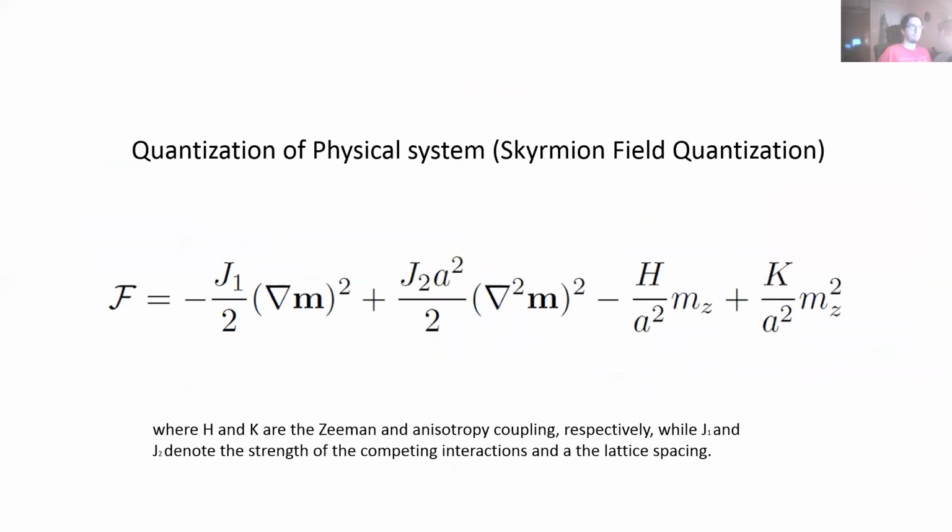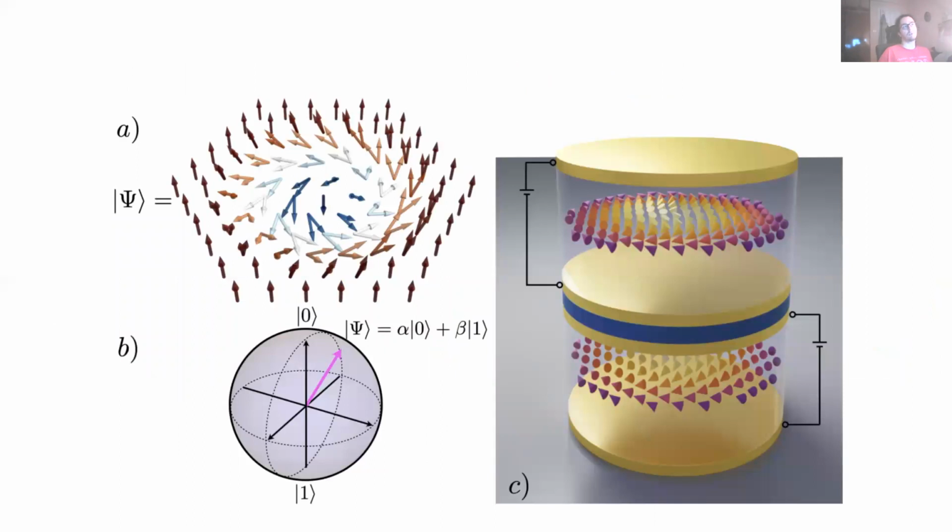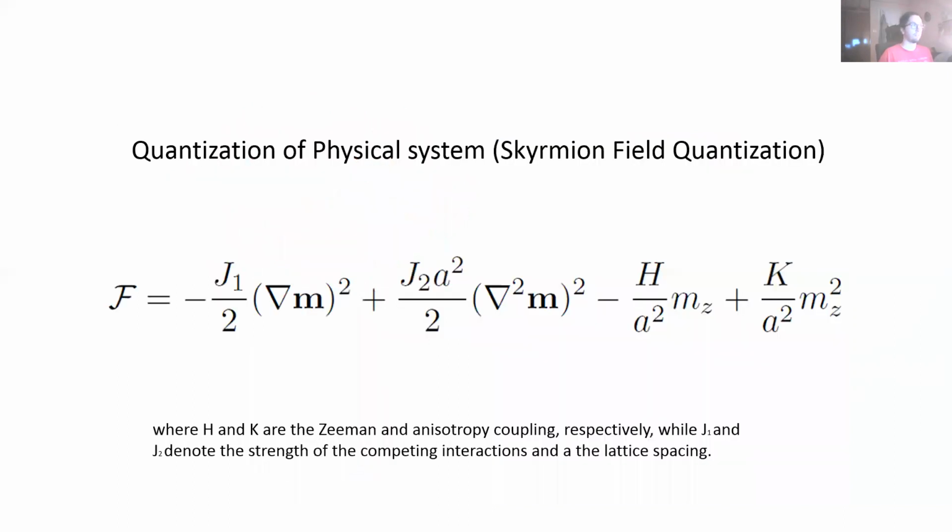In this picture, you can see that the Skyrmion structures are stable in nanodisks, so their translational motion is disregarded. It's not a degree of freedom for this offered system. But the degree of freedom that can be used is the helicity, so precession of each magnetic moment by external parameters, and also the Sz magnetic spin angular momentum phenomena.